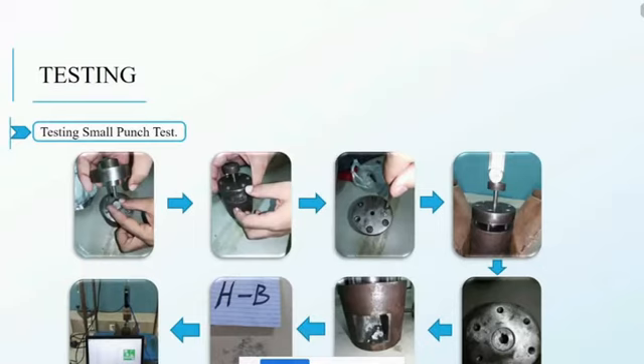It has an upper and lower die. We apply the load in this area, sorry, in this one, and the sample will be put as what we can see here. And we apply the load until we fracture the sample. Then we record the loading and the stress, and we do the microscopic analysis after the fracture.